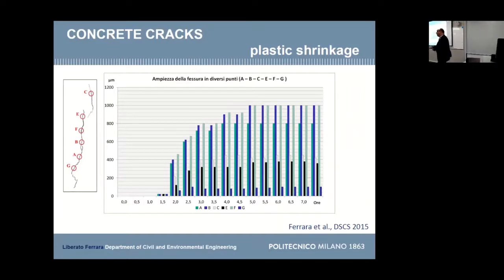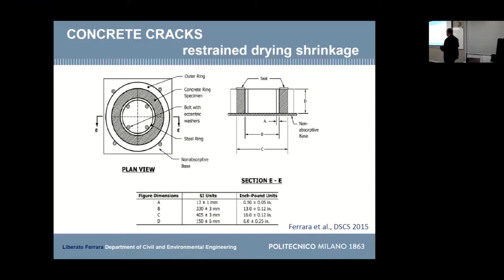And this is, for example, one of the cases in which any self-healing technology may help, because these cracks immediately appear. You can hardly do without them. You can check the curing status and so on. But if you have something which helps in closing them, we use it in this case, pre-soaked lightweight aggregates, which helped in some kind of self-curing, I would say, supplying water. We were able to cope with that.